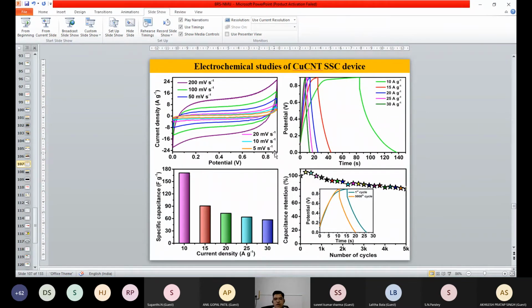So it is not like vanadium oxide or vanadium sulfide, which gives a voltage window of above 1.5. So the voltage window is limited in this one, and for stability we reached 5000 cycles, with about 80% retention. And also we have done some charge discharge studies, the potential versus time graph, from this one.